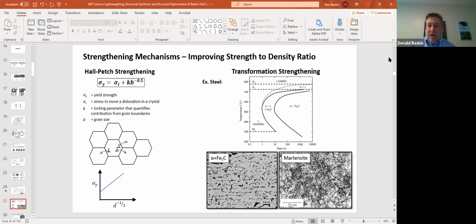The next strengthening mechanism we're going to talk about is transformation strengthening. This is very common, say, in steels. You get a steel from the steel mill, and it's a nice and soft annealed steel. It's made out of ferrite. The ferrite is very soft, has few dislocations in it. This ferrite can then be solution treated at like 870 degrees Celsius.